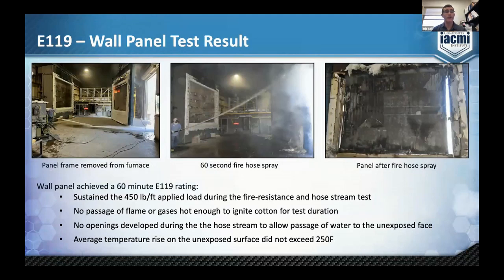Here's after an hour, the panel frame was removed from the furnace. You can see the fire hose spraying at it there. And then here's the panel after the fire hose. So you can see that inner laminate is pretty much destroyed, but for an hour you got up to temperatures close to 2000 degrees, which is enough to actually destroy even the glass. So this panel achieved a 60-minute E119 rating, which is pretty darn significant for a composite structure.